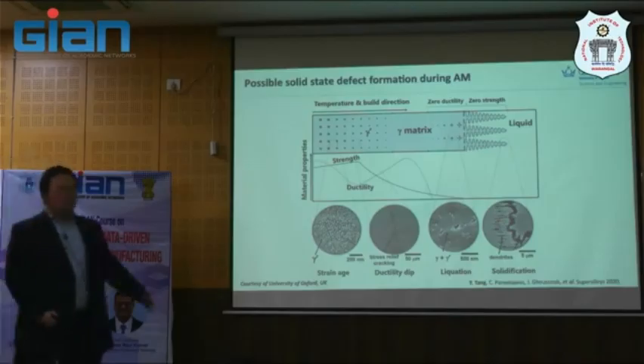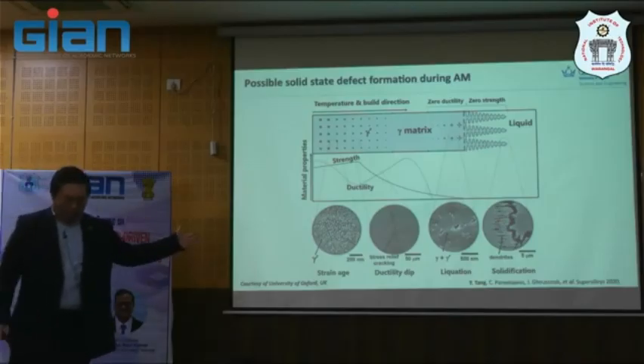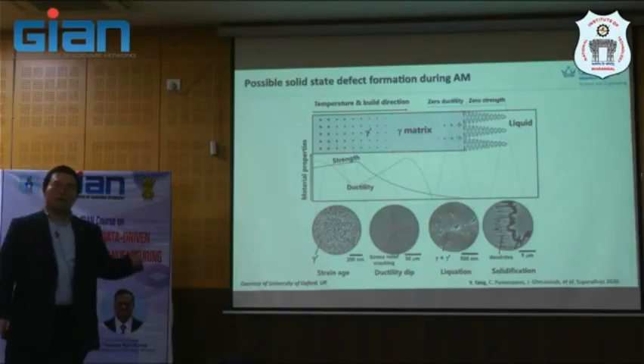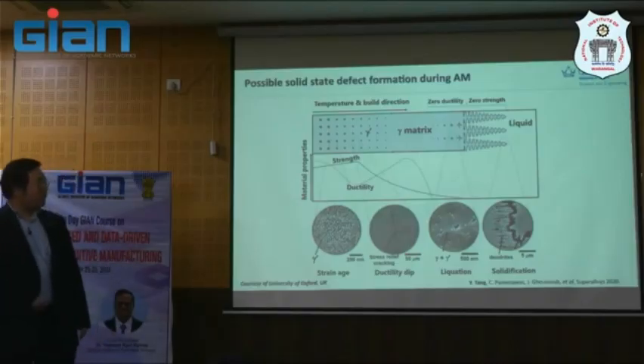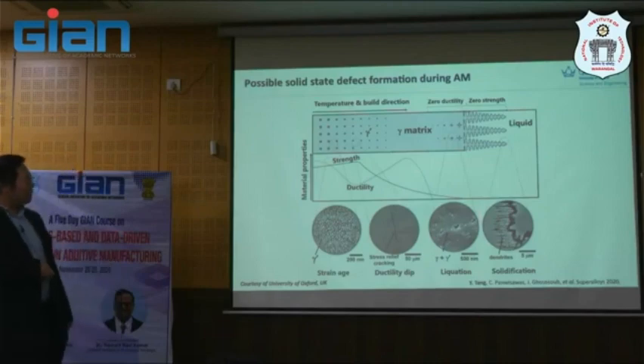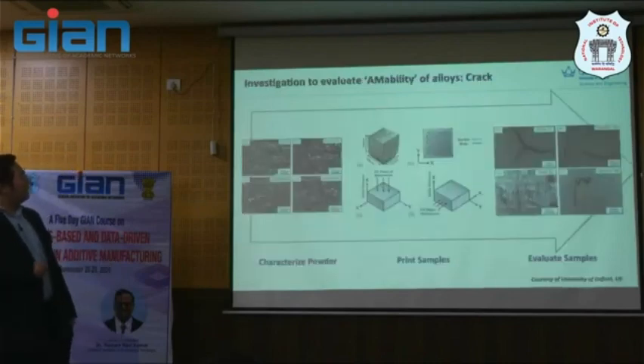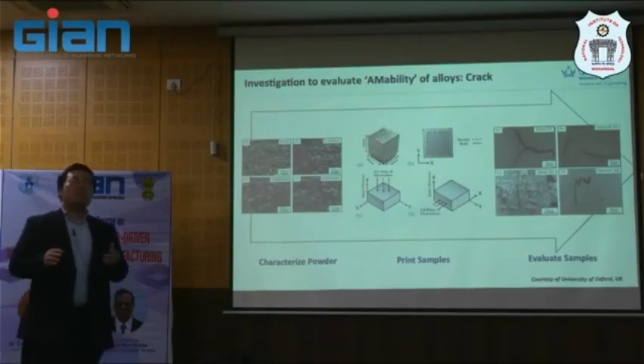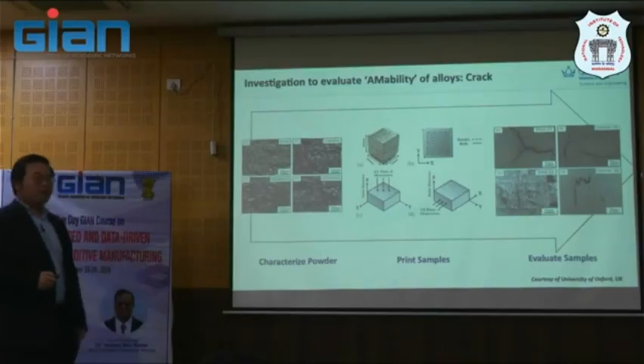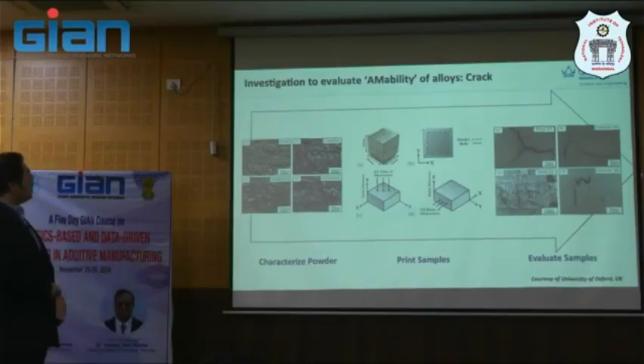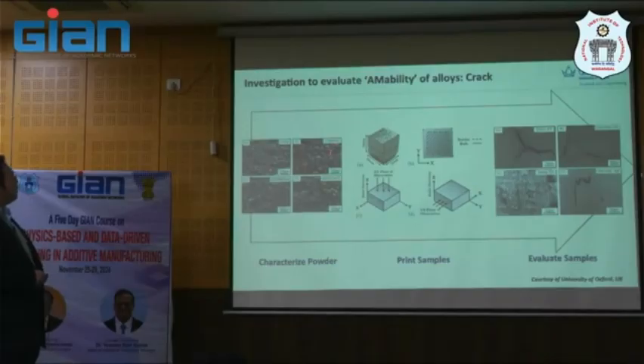So I think this is good. Tony Tang, my previous postdoc, now assistant professor at University of Birmingham, has done this very well. And then what we did next is try to systematically investigate the crack which is present during the 3D printing in 4 nickel-based superalloys. So if you remember, we introduced 2 new nickel-based superalloys, ABD series, ABD 900 and ABD 850, and then compare with Inconel 939 and CM247.